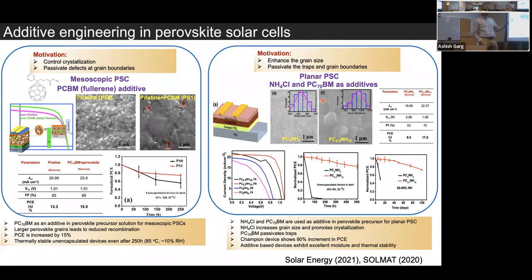So if you use ammonium chloride, and this is about the role of chlorine. When you put a little bit of chlorine in the perovskite lattice, it goes to the grain boundaries and changes the grain boundary energy in a positive way, so that the grain size, if you notice this one without the additive and with the additive, the grain size is significantly larger. And this leads to significantly improved performance, not only the efficiency, but also the lifetime.